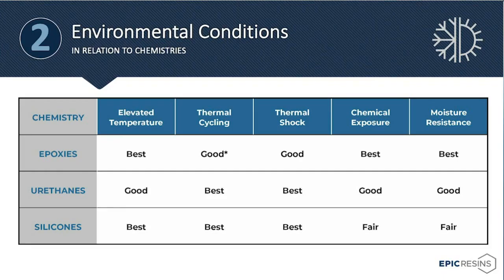So now we're going to compare these three chemistries of epoxy, urethane, and silicone in these different environmental conditions. When we compare epoxies, urethanes, and silicones for elevated temperature exposure, epoxies really perform the best of these three chemistries. And that's, again, primarily because of the cross-link density. As we have a higher cross-link density, those polymers have better elevated temperature resistance.